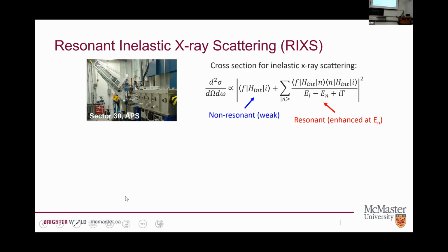Okay. So I won't spend too long on the technique here, other than to say that resonant inelastic X-ray scattering is similar to other inelastic scattering techniques, except you tune the energy of your X-ray beam to a particular atomic absorption edge. And so that blows up one of the terms in the inelastic scattering cross-section that makes normally very weak inelastic scattering strong enough that we can measure it.